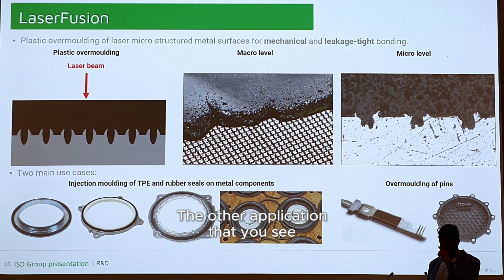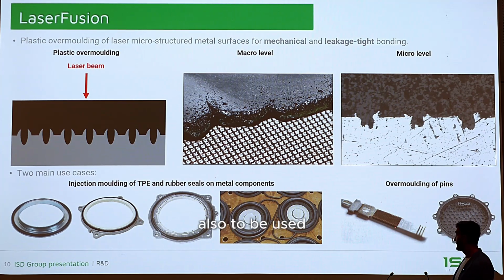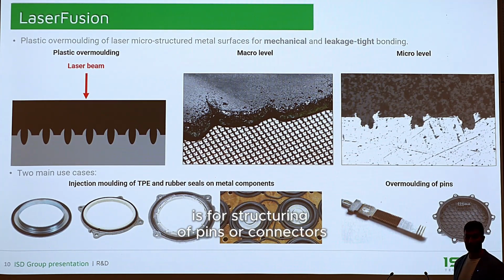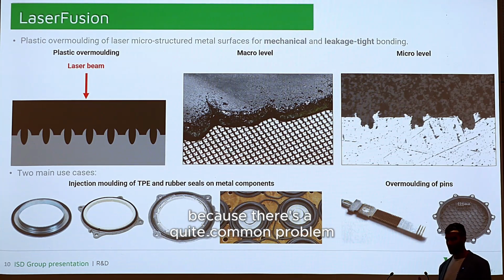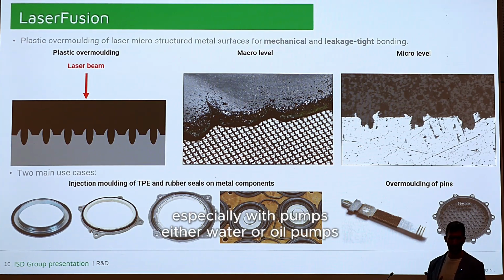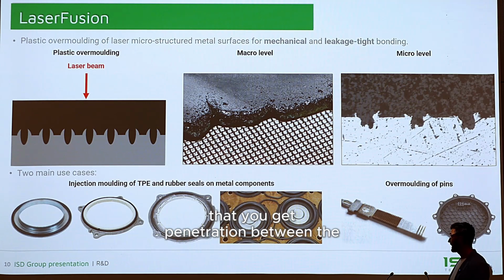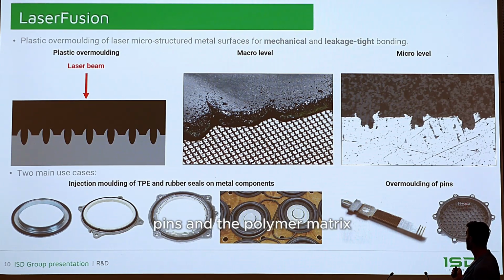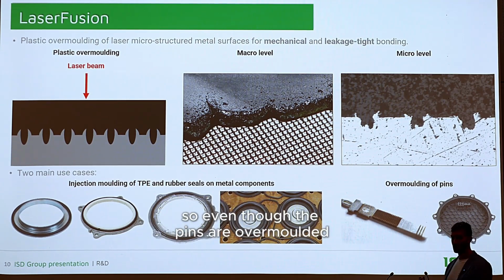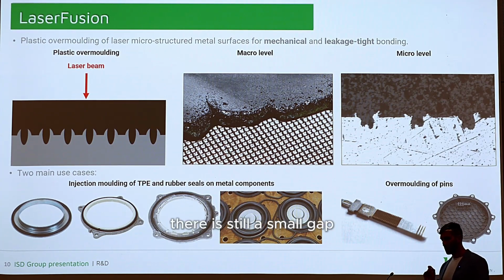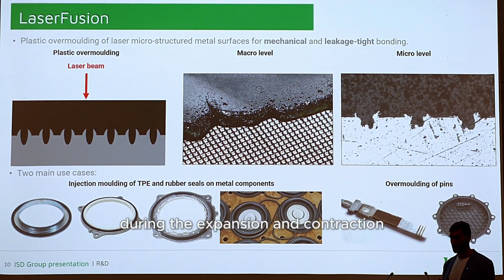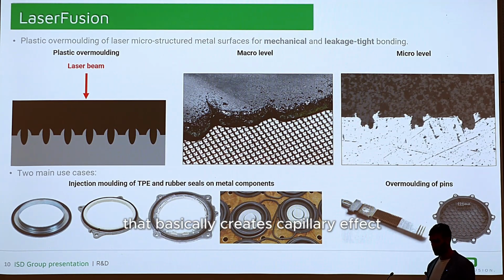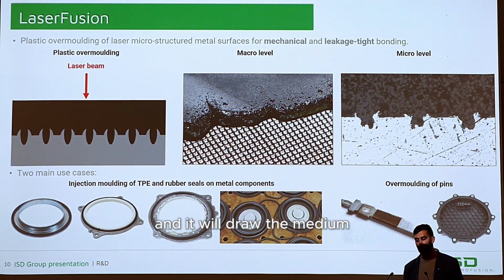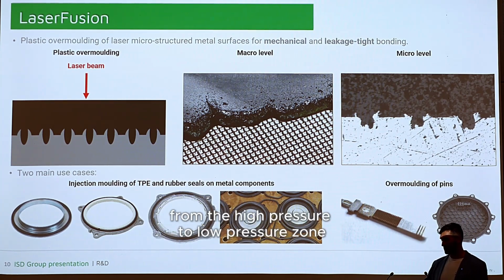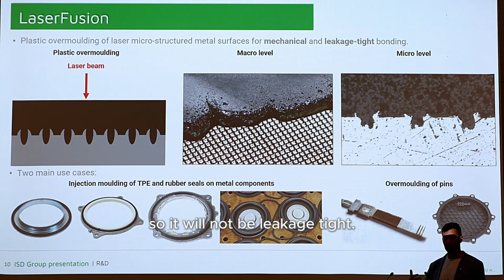The other application that we see also to be used is for structuring of pins or connectors, because there's quite a common problem, especially with pumps, either water or oil pumps, that you get penetration between the pins and the polymer matrix. So even though the pins are overmolded, there is still a small gap during the expansion and contraction that basically creates a capillary effect, and it will draw the medium, let's say oil or water, from the high pressure to the low pressure zone.